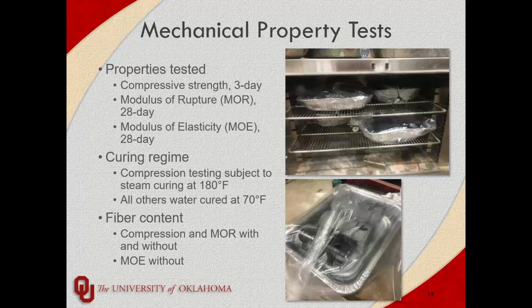So as I mentioned before, the properties we tested were typical characterization properties: compressive strengths, modulus of rupture, and modulus of elasticity. One thing that is pretty common with UHPC is heat curing. If you heat cure it, you tend to get slightly higher strength. So we decided to do compressive testing heat cured to see how well it compared. We also adjusted the level of heat curing, because at the time there was no ASTM available for UHPC. So we were trying to come up with our own heat curing regimes that we could give to ODOT. And we looked at different heat curing methods, and one of the best ways we saw was putting them in an oven in a little tray that's filled about halfway with water, so it sort of mimics steam curing. We got it up to about 180 degrees Fahrenheit, and we cured it for various amounts of times.